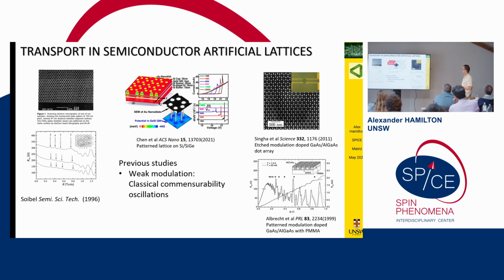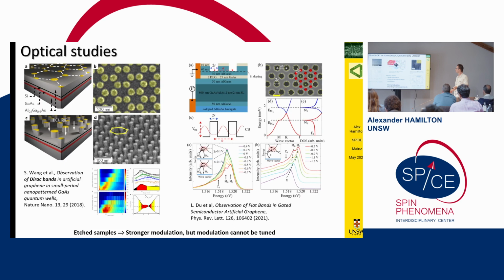And in all these previous studies, what you can see is that you get a weak modulation of the electron gas, and so that causes a small correction to the quantum transport properties. But when you try and get a strong modulation, the disorder kills you, and you just end up with a disordered insulator. Optical studies have been more promising, and you can etch down and create a strong modulation. And there is evidence of forming Dirac-like bands by creating a honeycomb lattice on a two-dimensional system, but the modulation can't be tuned. So you're sort of stuck with, once you've made the sample, that's it.